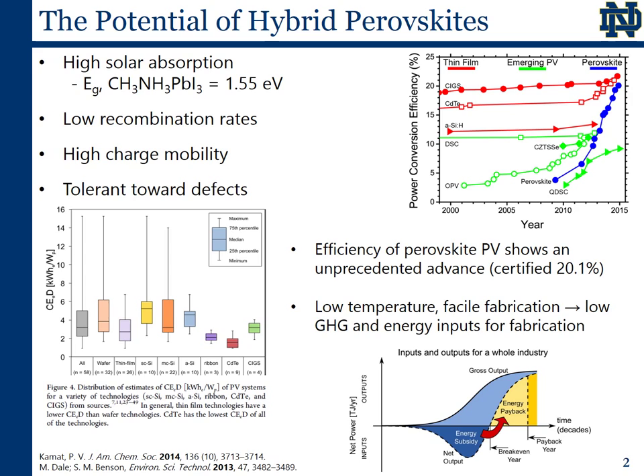Hybrid organic-inorganic perovskites have recently received significant attention throughout the photovoltaic community. In particular, the compound methyl ammonium lead iodide has demonstrated near ideal band gaps, low recombination rates in solution processed films, high charge carrier mobilities, and a high tolerance toward defects, which has driven an unprecedented rise in the solar cell efficiency, from less than 4% in 2009 to a certified efficiency of 20.1% today.